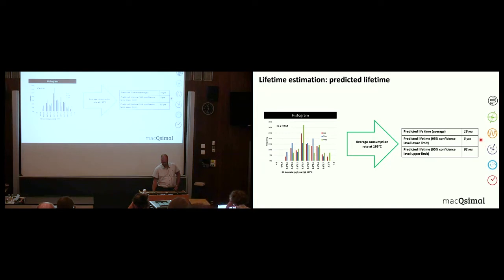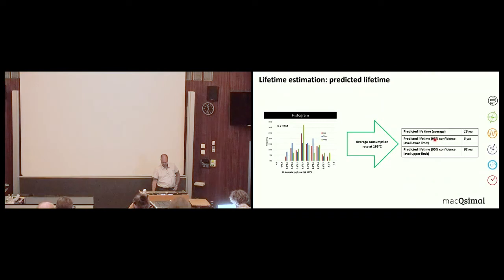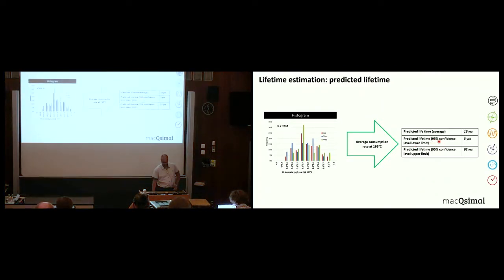And these measurements of this thermal aging now at 160 and in particular at 110 degree will allow us to bring this predicted confidence level closer together so that we have a little bit a better view on the predicted lifetime.